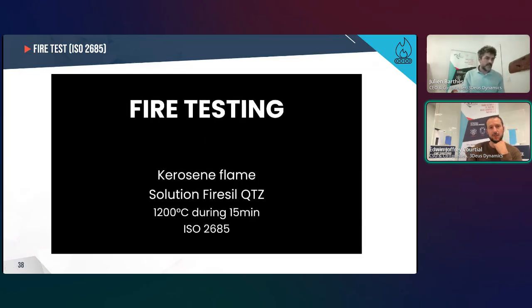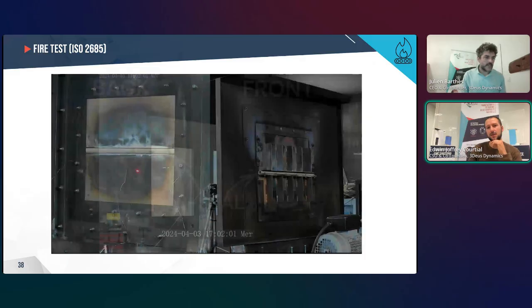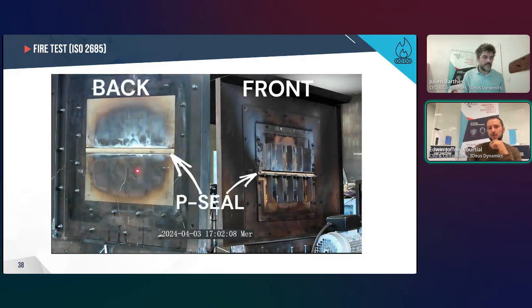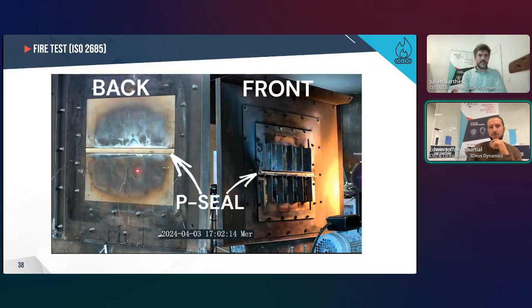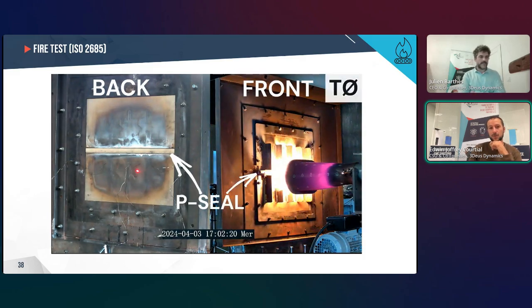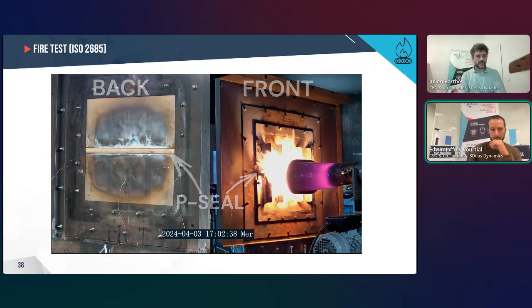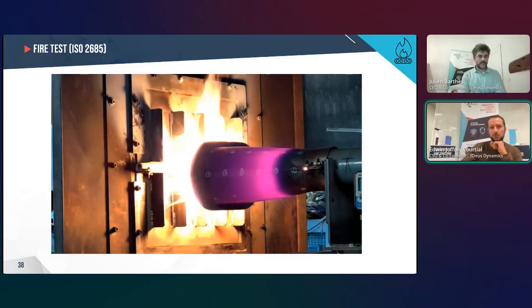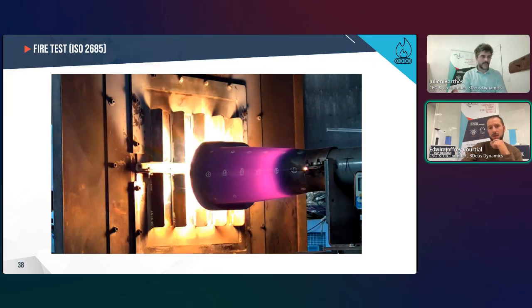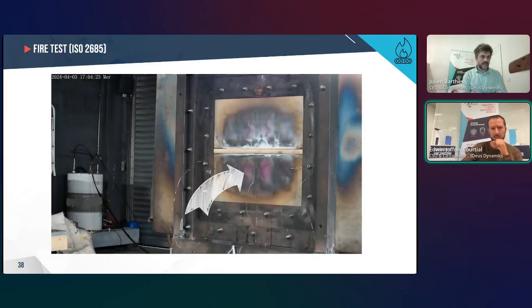Yes, thanks, Julien. This video illustrates the fire-resistant test performed according to the ISO 2685 standard. In this protocol, we evaluate a fire stop joint produced by dynamic molding made of silicone combined with a mineral powder, which is QTZ grade in 3 layers. The sample is exposed to a kerosene flame at a fixed temperature and heat flux density, representative of the conditions faced by aircraft structures during engine or external fire.